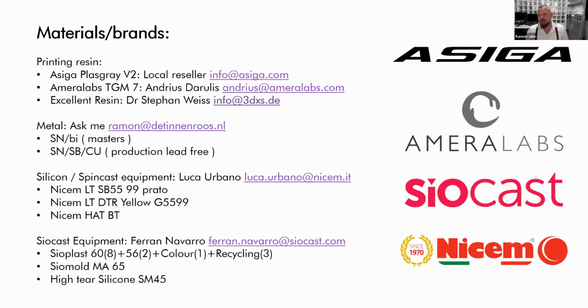Yeah. For the metal, what we use in the company, just send me an email and ask me. We use a tin bismuth alloy for making our metal masters. And bismuth is a very, very nice material because it's expanding from liquid to solid. So when you have this model in your mold and the model is cast and it starts to cure, so it has to be solid, it expands a little bit. And normally you get some shrinkage, but with making the masters of tin bismuth, there is almost no shrinkage at all.